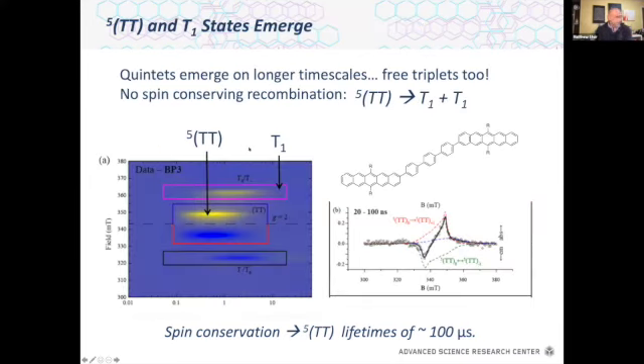What we also can see is that quintet states and things that look like uncoupled triplets emerge in our molecules, even without diffusion. This is a similar molecule to what I showed you before, except we've just pulled the chromophores spatially apart. And this is with spin resonance, not with optical spectroscopy. What we can see is unambiguous signatures of a quintet state, and the quintet state over time will decay, and over time we can see the formation of something that looks like an individual triplet. And I'll give you a sense of the dynamics at the end.